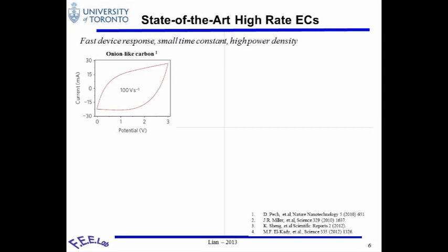First started with Patrice Simon and Yuri Gogotsi's group, using onion-like carbon, and they published the paper in Nature showing that they can deliver 100 volts per second, that kind of high rate. And by the way, this is a CV, and for those who are not familiar, you are looking for a rectangular current voltage response, and that's the one that shows the most capacitive behavior. So this is something that's been published to show 100 volts per second, which is a very, very high, fast rate in terms of when you apply the voltage scan and the current can respond. And in that case, we got about 0.9 millifarads at this rate.